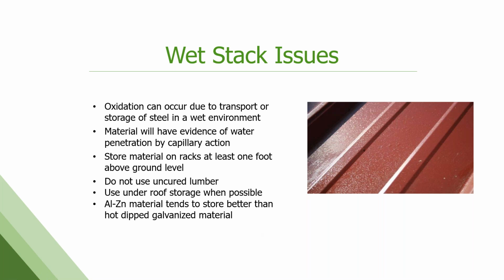Wet stack or storage corrosion is another issue with pre-painted metal that can be quite serious. When the panels are in bundles being transported or stored, they're very tightly packed together and there's very little air movement, but moisture can still get in between them. And when you have moisture without the presence of air, that allows that moisture to migrate to the surface through the paint and cause corrosion underneath the painted surface. And the paint starts to bubble up and you get this sort of rough blistered appearance.